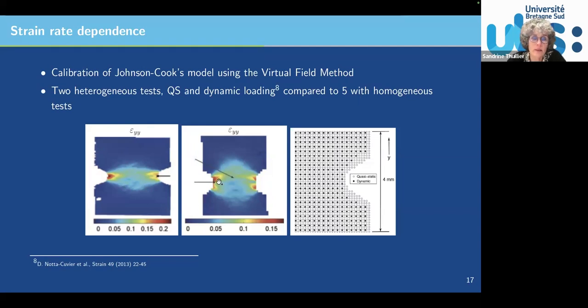So the idea is that you have a strain distribution, but you also have a strain rate distribution within a single test. And using this strain rate distribution over the sample, you are able to calibrate, for example, Johnson-Cook, just for this given test. Of course, here you've got just an illustration because there are some limitations coming from the experiments. Because in the case of quasi-static loading, you use cameras which are different than in the dynamic test, because you need high-speed cameras in the case of dynamic testing, and you don't have exactly the same resolution, and you don't have exactly the same information. What can be illustrated is that you've got more information during quasi-static loading compared to dynamic. So there are limitations, of course, related to the experiments, and it refers to what I mentioned previously. The quality of your measure is very important within this approach.